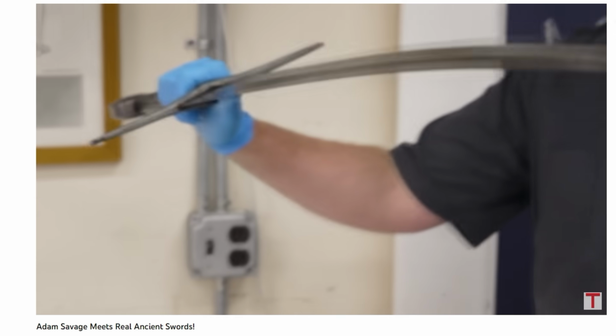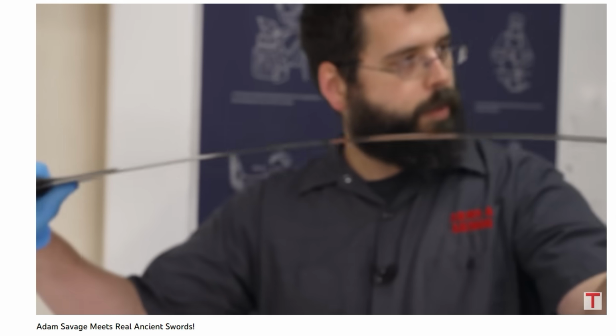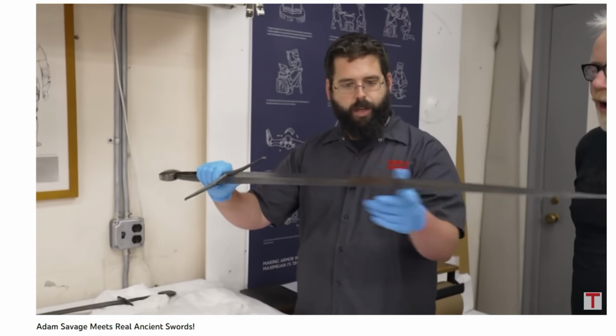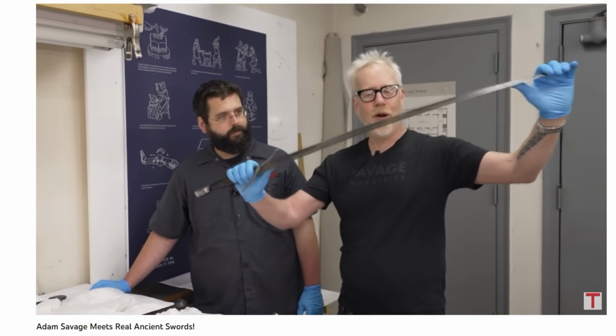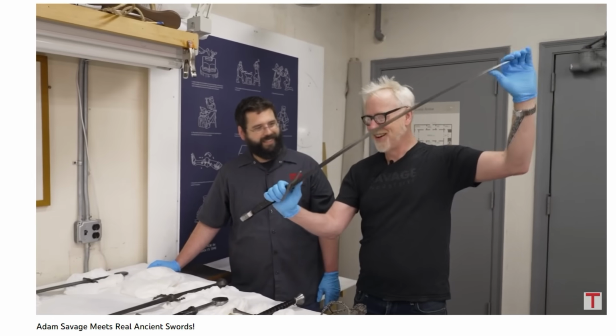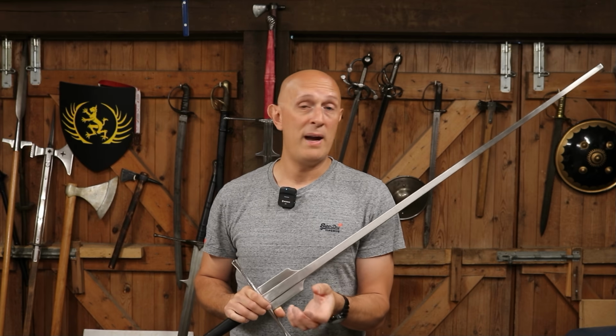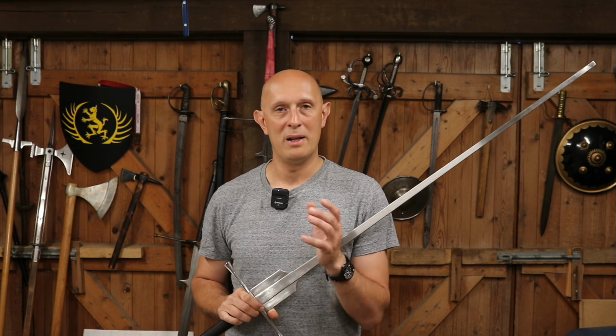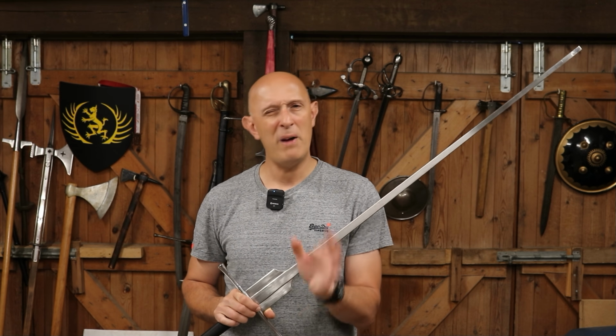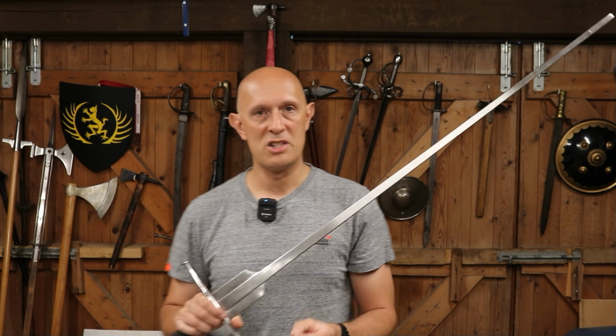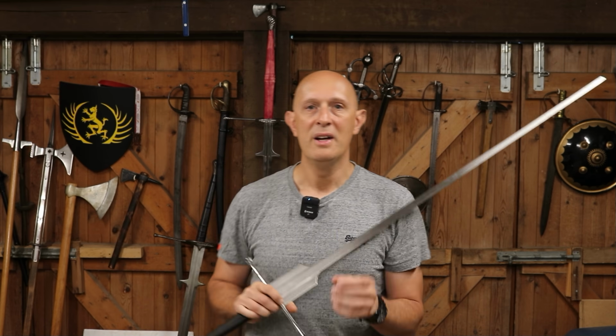You can see examples in the Metropolitan Museum of Art. Adam Savage's channel absolutely showed it. 14th, 15th century medieval swords are pretty much all springy as far as I've seen. Let's talk about the hardness for a second. Medieval swords that have been tested for hardness vary anywhere between about 25 Rockwell and about 45 Rockwell. Very occasionally as high as 50 in limited spots, but it's inconsistent.